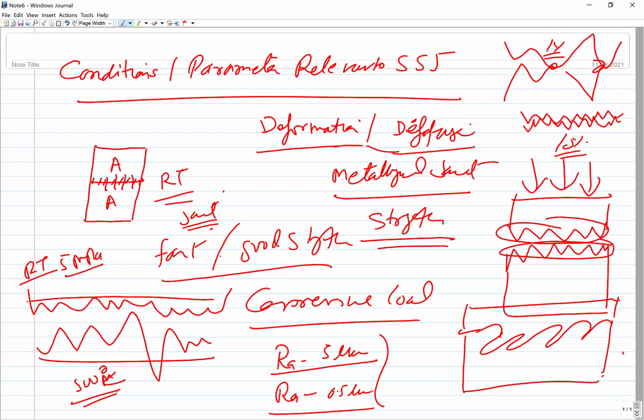So the role primarily here of the pressure is to just bring the two components so close to each other that there is a metallic intimacy. If the two components have come so close that the contact between them is almost 80%, like in all these areas there is a metallic intimacy. Okay. So obviously when it is established, diffusion across the interface is very stark because of the compositional gradients,